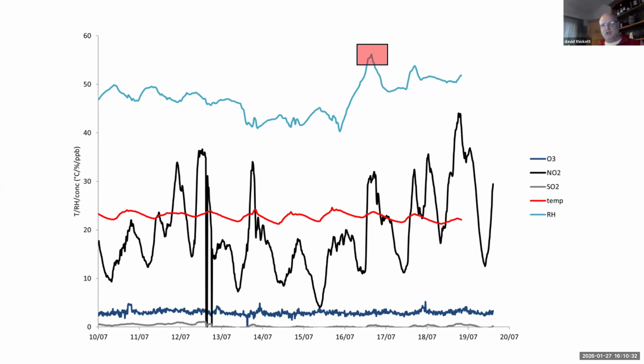And the traditional approach to this has been to set a range for the temperature and relative humidity and a value below which you want to keep the gas levels. And it's actually quite challenging with the information we have, some of which is contradictory, to choose what are appropriate values. And as I say, they change. And the way to do this would have been through chemical filtration, which puts a big resistance in the air path. So again, it's energy intensive along with controlling temperature and relative humidity.